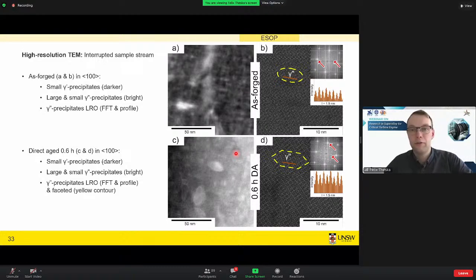So what we can show here is that we indeed already have precipitates in the as-forged condition, which then grow very quickly. Because if we just look at the atom probe, it might be just some accumulation of niobium. It might not be ordered, which would be a precipitate. But here we can show they are already ordered like they are later, after 0.6 hours. Yeah, which makes them precipitating particles.